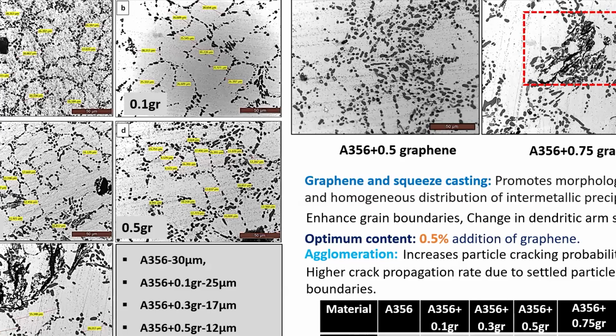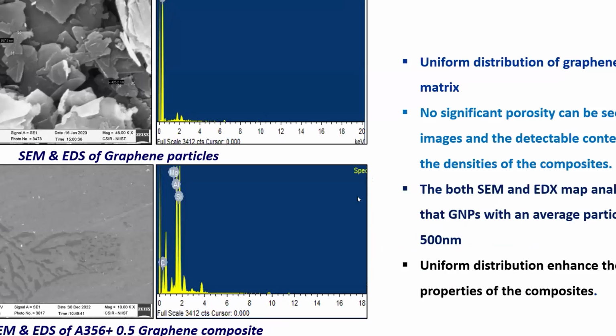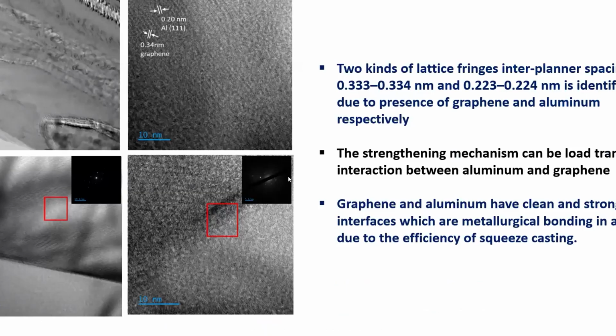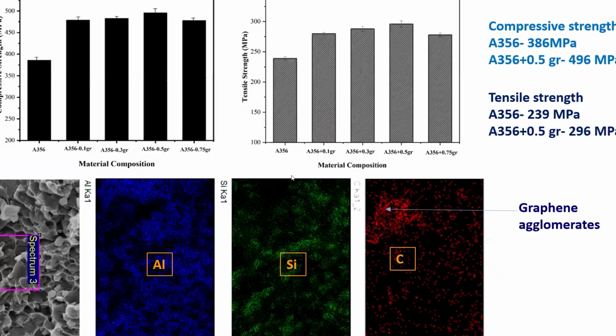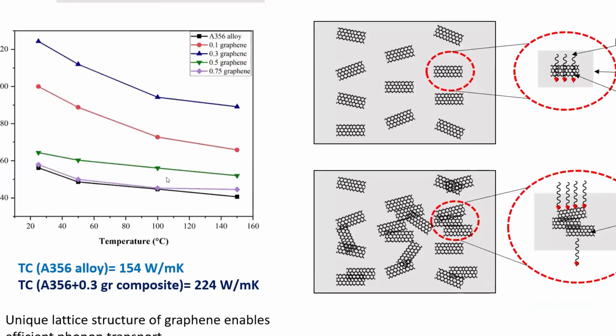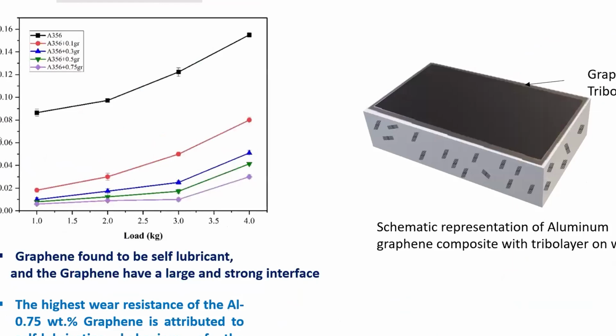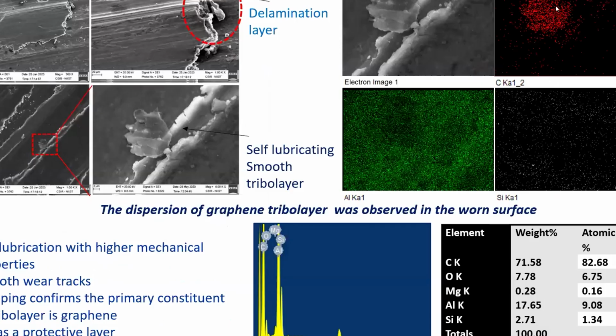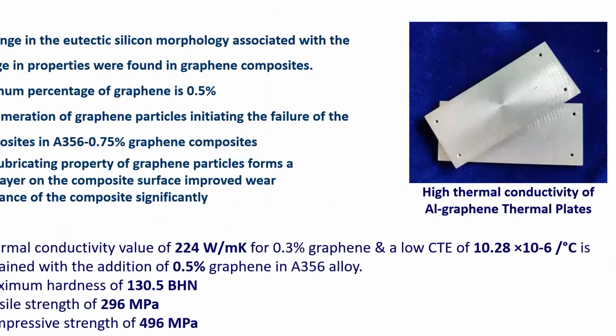We also studied graphene at very low percentages. I'll not go into the details of the study, but I will sum up the observations. Graphene addition also enhances the thermal conductivity, for example, 154 to 224 for 356 alloy. The wear resistance is again very high, similar to carbon, because of the self-lubricating behavior. Here we can see a mechanically mixed layer formed at the interface, which will not allow further wear. It will just give a lubrication layer when there is movement of any automotive or aerospace component. Overall, the thermal conductivity of aluminum graphene is higher, hardness is improved, and tensile properties and all the properties are enhanced.